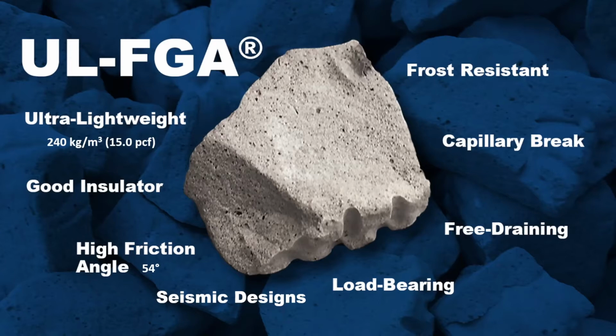Materials that have a lot of entrained air in them tend to be good insulators because air is a great insulator. We also have a high friction angle. In geotechnical engineering, the way that we describe the strengths of soils or aggregates is by their friction angle and cohesion. The higher the friction angle, the higher the shear strength you're able to mobilize at a given normal stress. And 54 degrees is what we typically see from the shear testing that we do.